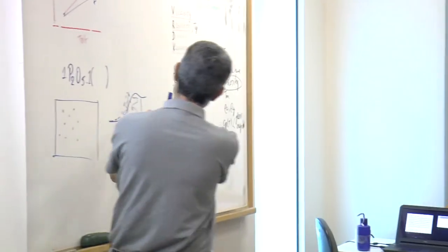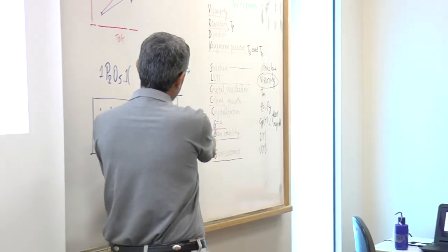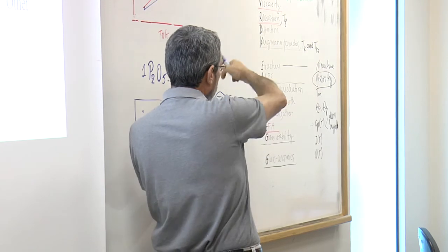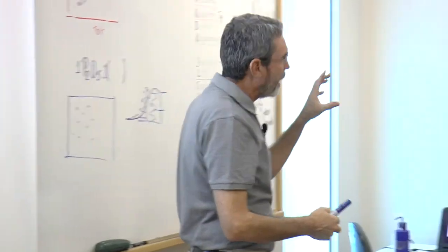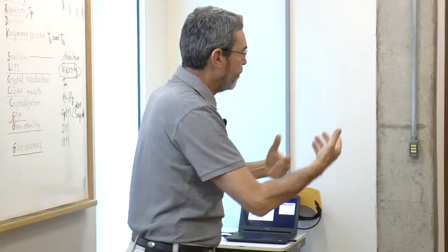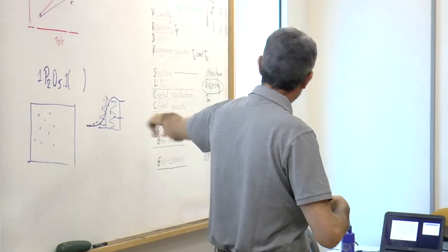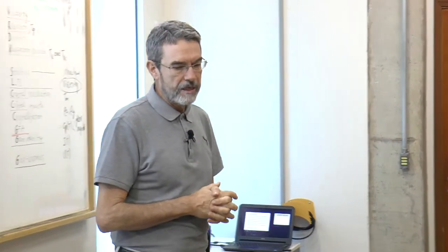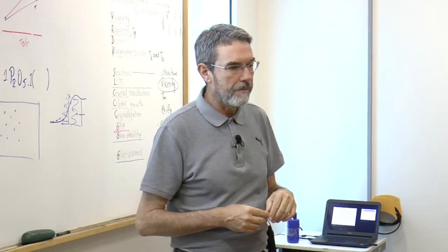Although the TGs will be similar, maybe 5 degrees Celsius or so, 10 degrees maximum difference, from the shape of the relaxation curve, which is indirectly reflected in the DSC, you can estimate the fictive temperature. I can give you the full reference later on. We have done this in our lab.